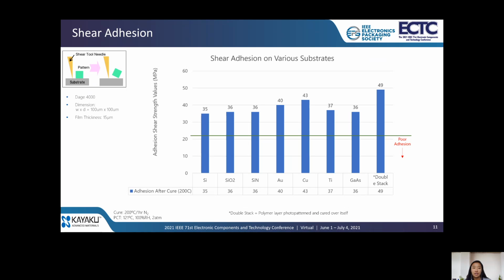And then these structures were tested on our Dage 4000 shear tool. So shown here is a schematic and initial shear adhesion values after cure. And then later on in this presentation, I will show how the adhesion is affected by pressure cooker testing. But overall, PRL 29 exhibits good adhesion on various substrates.